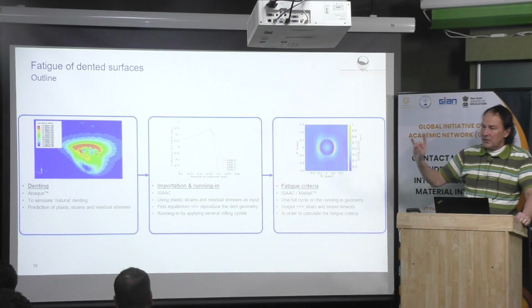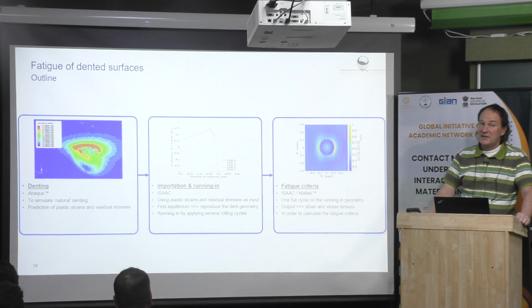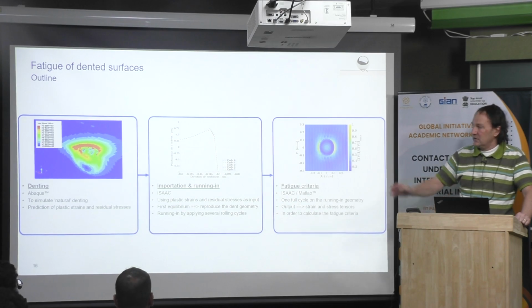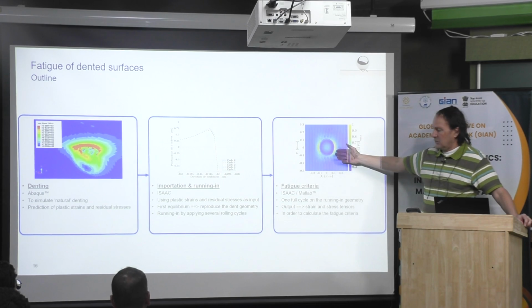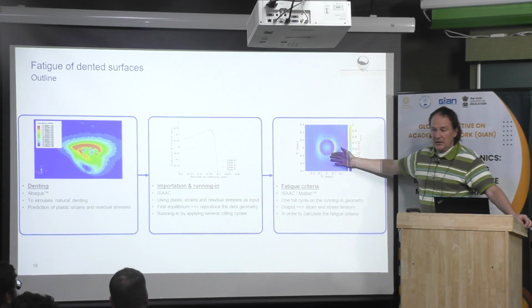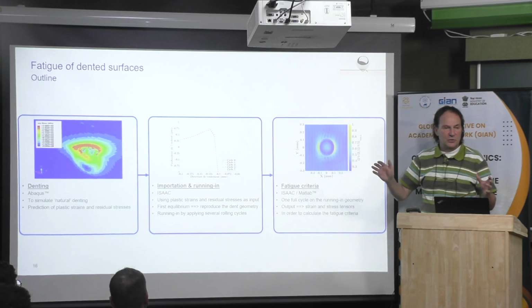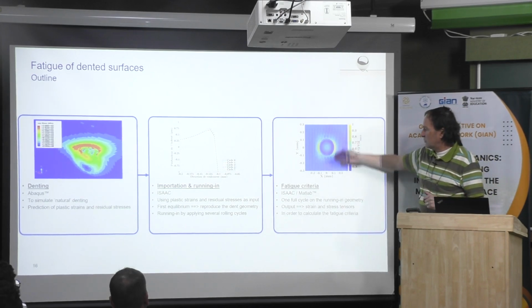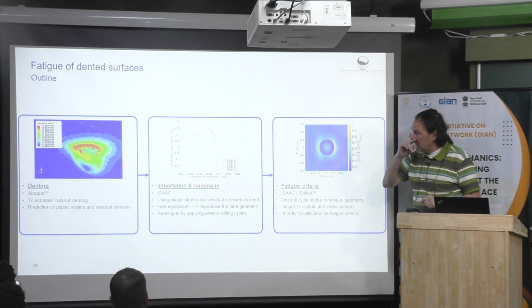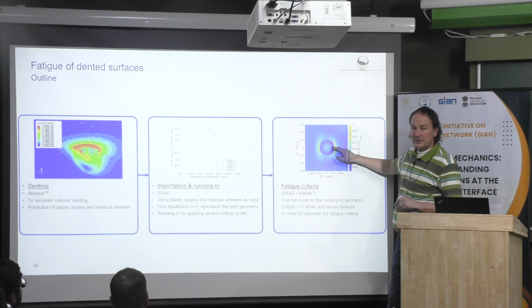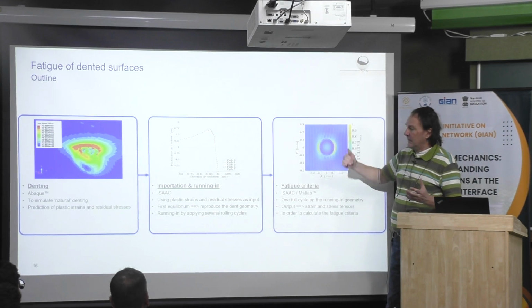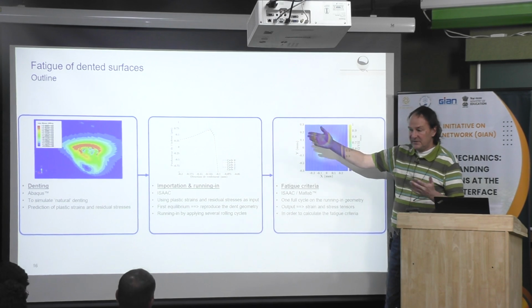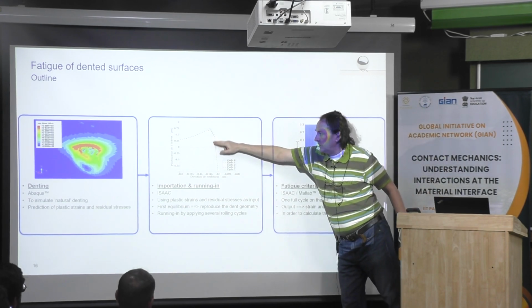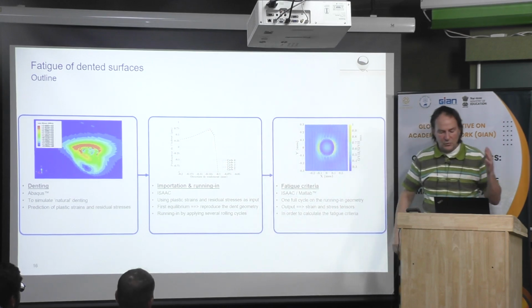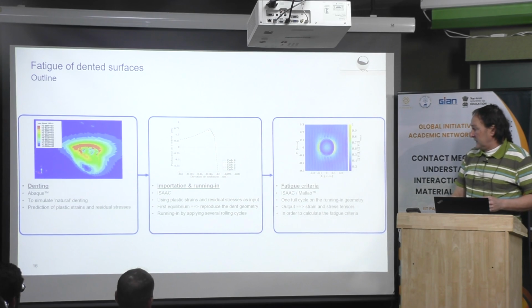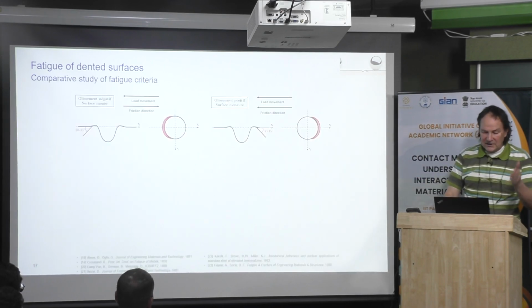When we transfer that, we transfer only the plastic strain or the inelastic strain. You don't have to transfer the residual stresses. Then you integrate that in the semi-analytical method, and you make the equilibrium of everything, and then you have the initial solution. And then after that, you may have the ball rolling several times. And also, you have to integrate the geometry of the dent. Then you have to integrate both the plastic strain and also the geometry, as you can see here, with a shoulder which is lower than 1 micrometer. And then you can investigate what happened after several cycles.